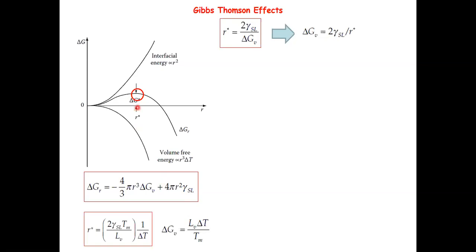And then we put these two terms together to analyze what the overall free energy difference looks like, right? First we fix a degree of supercooling, we fix delta T, so this delta GV, the free energy difference per unit volume, is fixed. And then this free energy difference is only a function of the radius, or the size, of the nucleus, if the nucleus is a sphere, right?